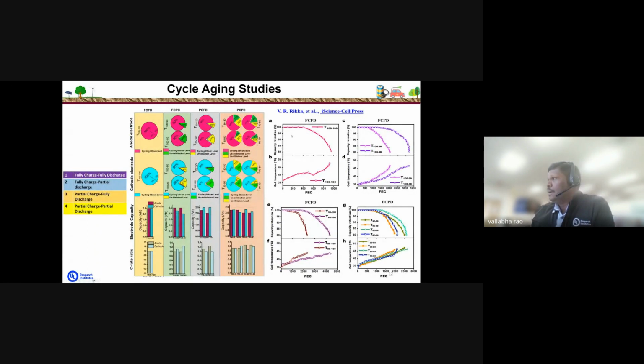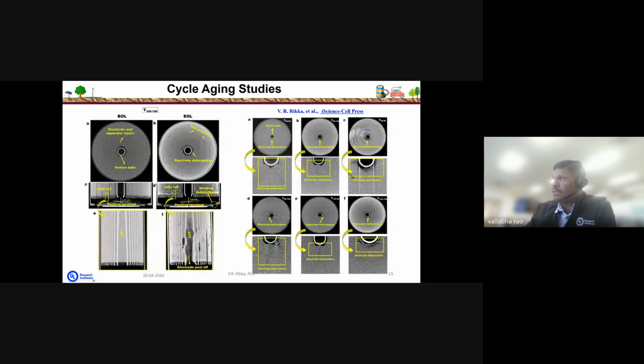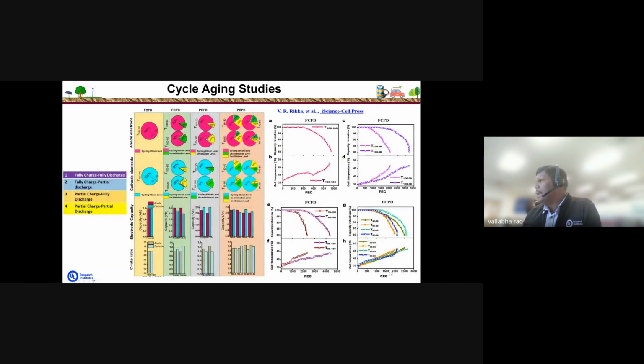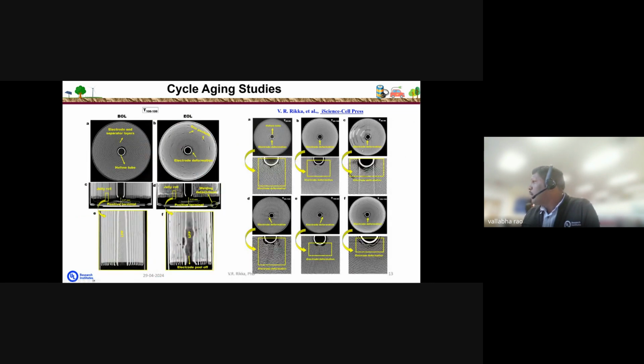As we can see here, over the cycles the cell temperature also increases. This cell temperature causes the evaporation of the electrolyte within the jelly roll, and it causes this kind of deformation by forming gas pockets. Along with the gas pockets, for this full charge and full discharge condition, we can see even electrode deformations occurred in the jelly roll. If you compare with the other test conditions which showed the highest cycle life, for example 3000 to 4200 cycles, which is more than 10 years lifetime, the deformation is still very small.